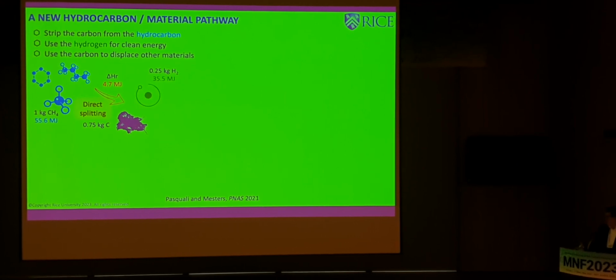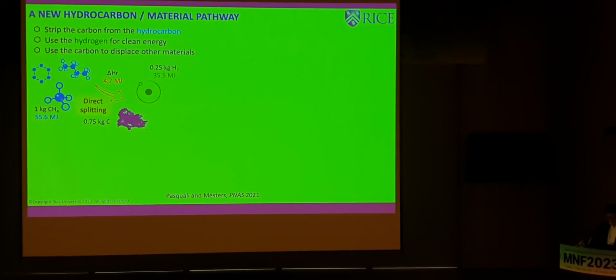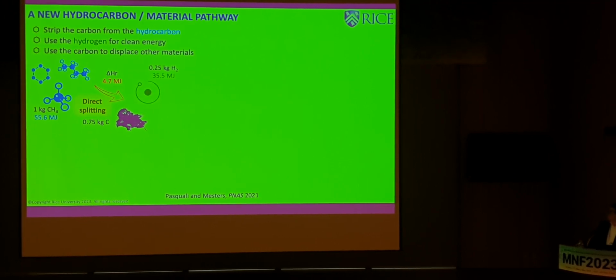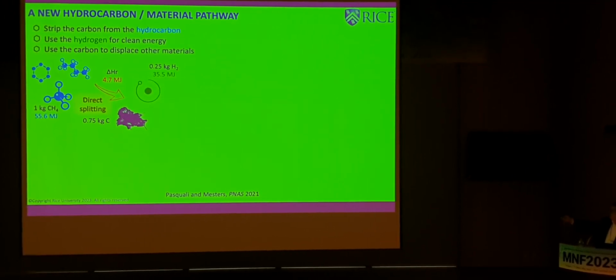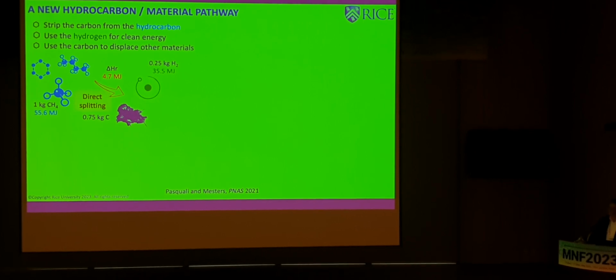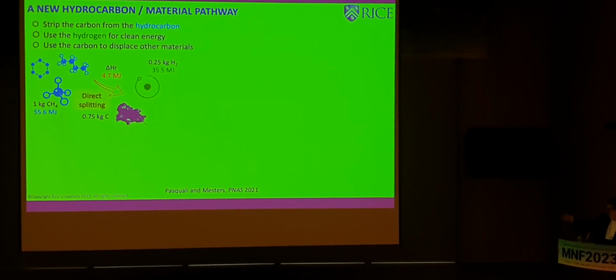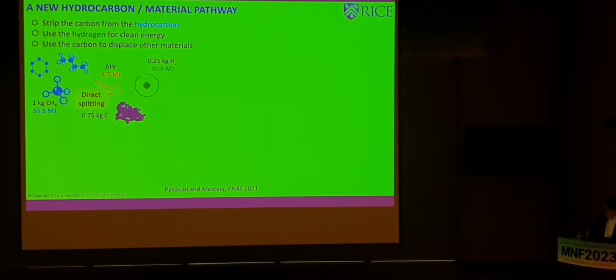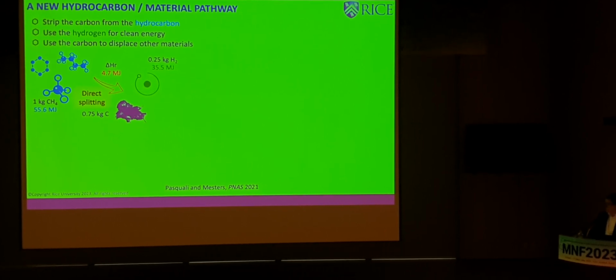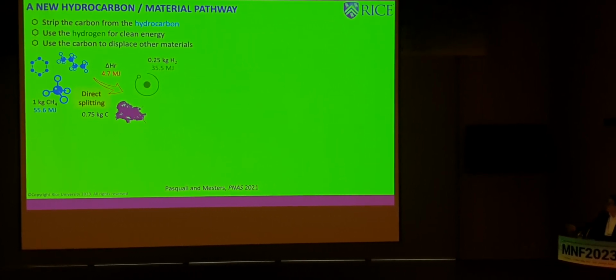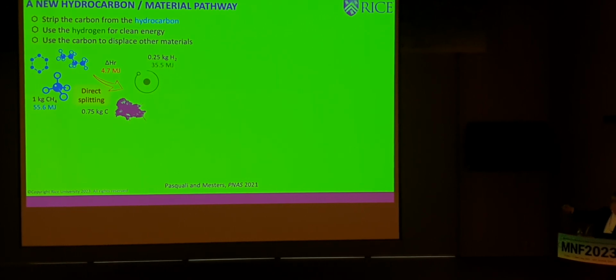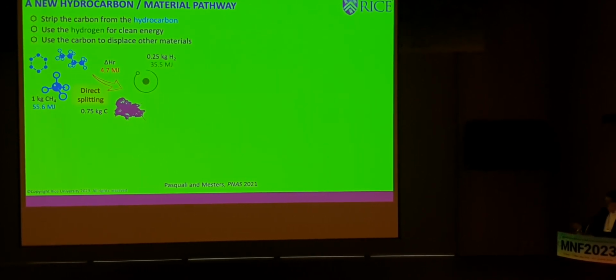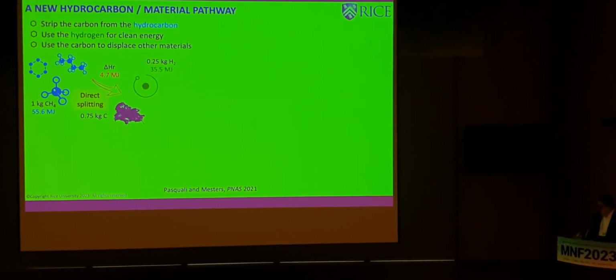And so the pathway is something like this. Again, if you're interested, this was published in PNAS about 2 years ago. You start with hydrocarbons, could be natural gas, could be other volatile hydrocarbons. We know how to make carbon nanotubes from pretty much any of these molecules, and more. Or it could be ethanol, right? It's just fine. You split it. This is for methane, so you get more hydrogen if you split methane. Some of the other hydrocarbons give you less hydrogen.